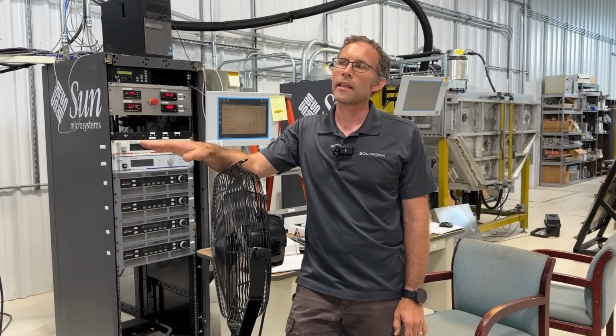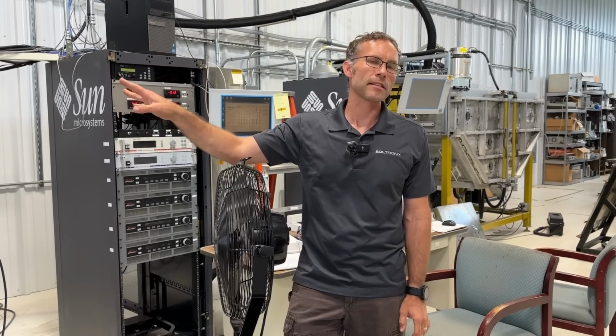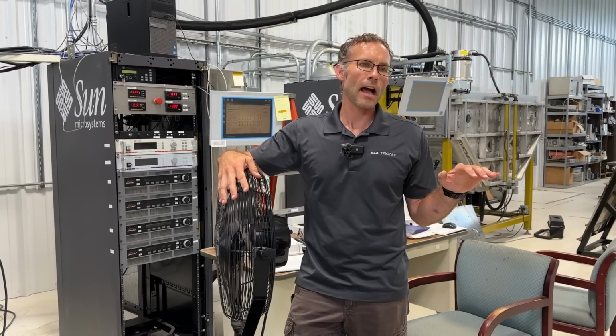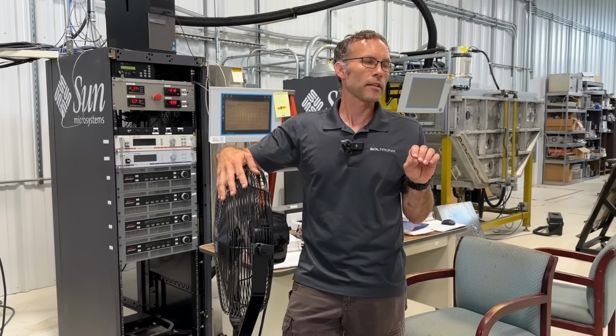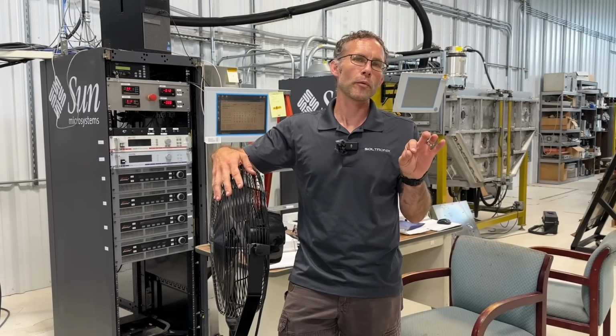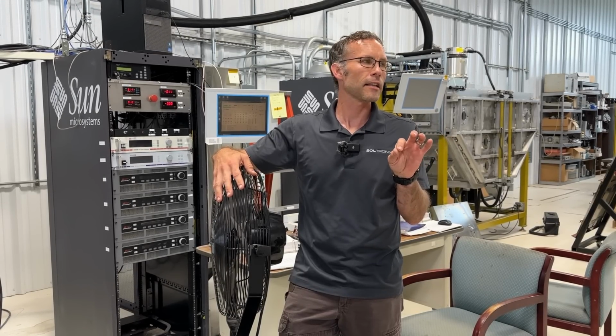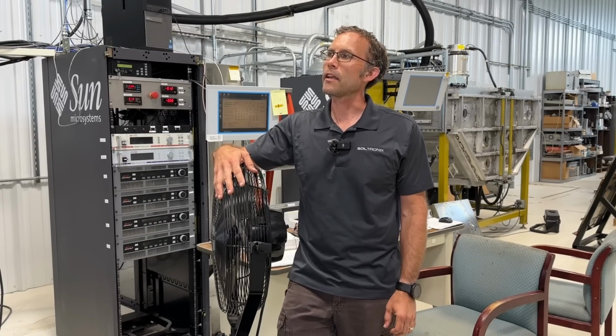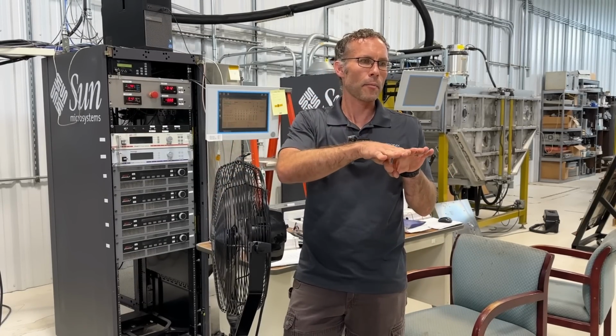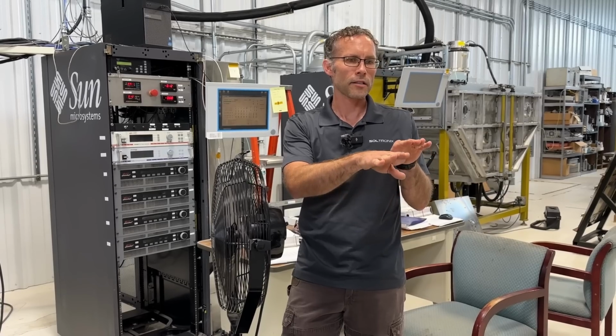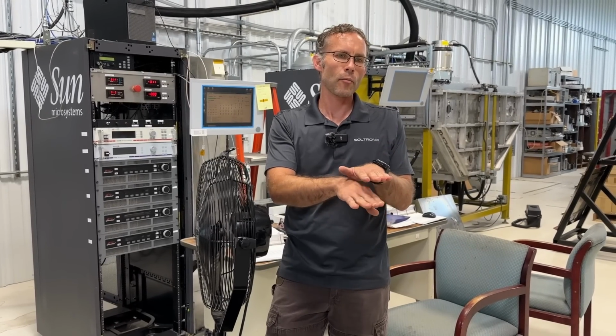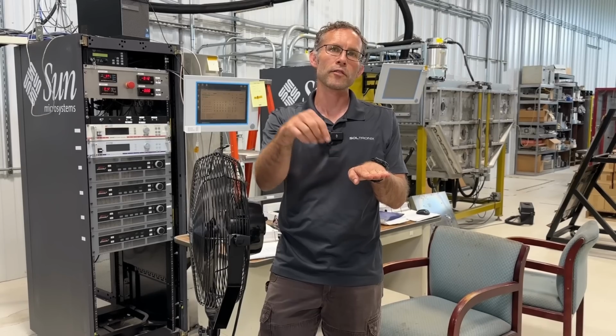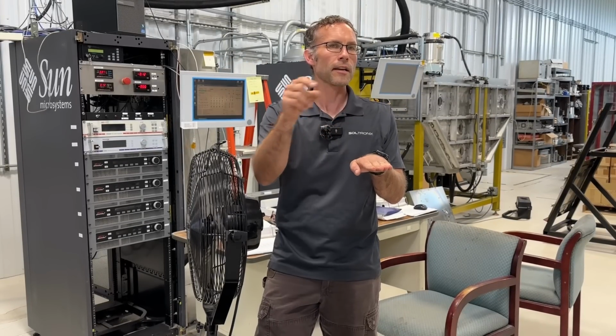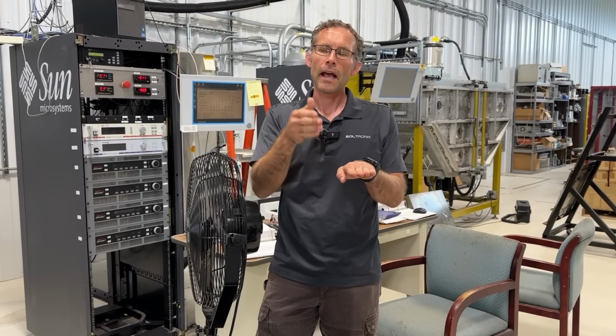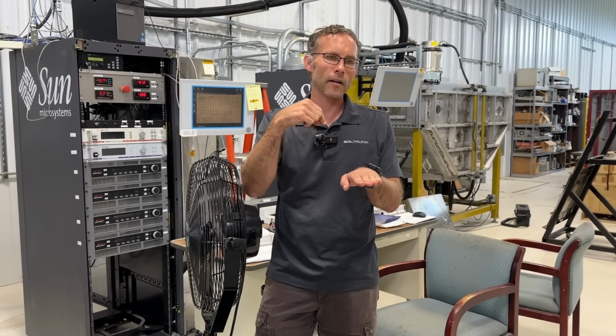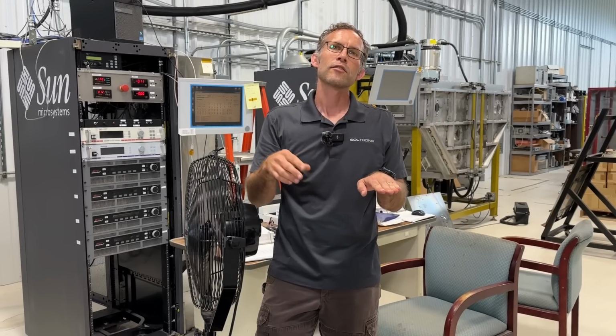Once the ITO is down, then the material again goes back and visits the lasers, and it actually gets the ITO scribed on top with the laser. It's a really shallow scribe because you only want to go through the ITO into that insulating layer that we had put down initially, and it just basically cuts the cells apart on top. So the first scribe we do, the through scribe, cuts through the whole silicon stack in the metal. The second scribe we do connects the silver down to the aluminum. So the silver from this cell here to the aluminum on the next cell, so top to bottom, to get them series strung. And then the last scribe is the top contact cut, which basically cuts the ITO between each cell so that you aren't shorted on top.